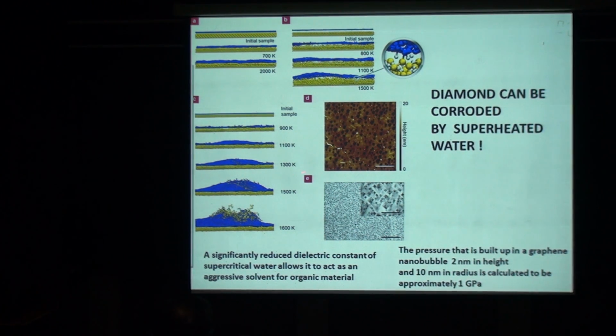But nonetheless, what is the pressure that's inside the bubble? Normally diamond can be corroded if the pressure is very high, hundreds of megapascal and above. If you do a simple calculation, based on the fact that you have to strain the graphene to form a curvature like this, you can calculate how much pressure is needed. It's almost gigapascal range. So we guess the pressure inside this tiny bubble is gigapascal. But what is the proof?